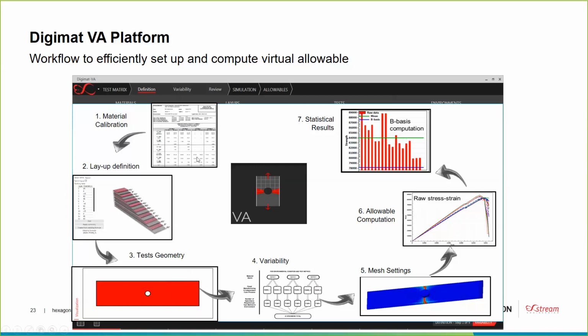So once material data, layup, and test configuration have been defined, we can go for the resolution. So it means that here Digimat-VA will create a finite element model corresponding to each configuration and is going to solve this finite element problem. So solving the finite element problem means that we are going to extract the stress-strain curve, and we will consider that the allowable is the maximum of the stress-strain curve. After this, we do post-processing. If we have defined variability, then we will be able to extract, for example, a mean value over all the configurations or a B-basis. If we haven't defined the variability, then we will have a single value which will correspond simply to the single strength value, or single maximum of the stress-strain curve.